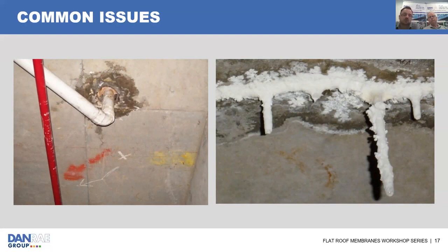On the picture on the right is your efflorescence, the salting that comes through a concrete crack. You can repair that as well with injection and a hydrostatic membrane that you can paint over the crack and secure that. But the same thing applies: because you're remediating it from the reverse side, you've got to keep monitoring that and ensuring that it's maintained, or have some kind of review to make sure the salts aren't continually coming through.